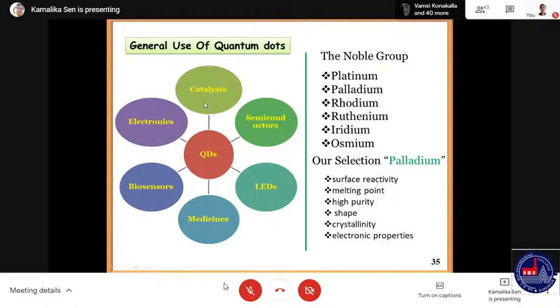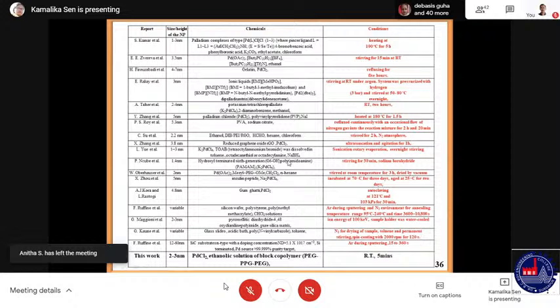Also, these quantum dots have catalytic properties, they have electronics. They are also reported to have been used in electronics as biosensors in medicines, light emitting diodes as semiconductors, and so on. And people have used different conditions in generating palladium quantum dots. You can see heating at 100 degrees Celsius for 5 hours, stirring, refluxing, then use of pressurized system, then 2 hours time which is required at room temperature, 180 degree, so many conditions.